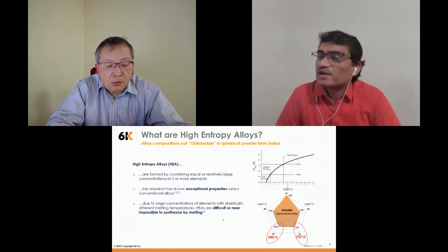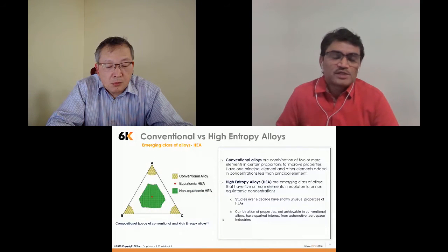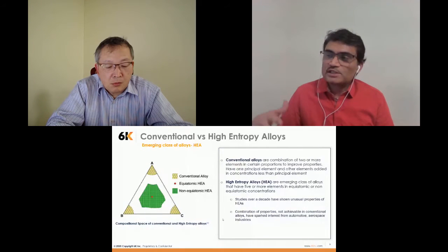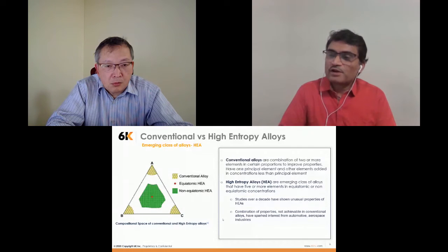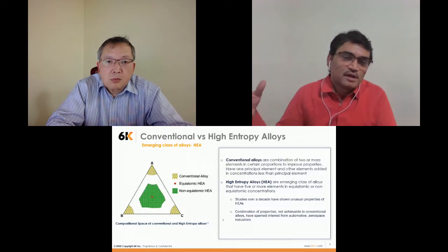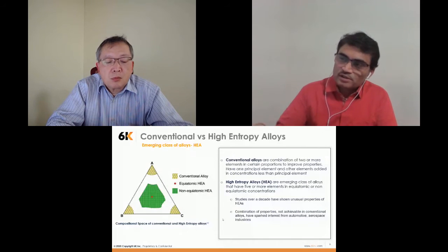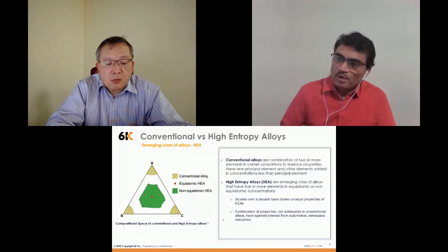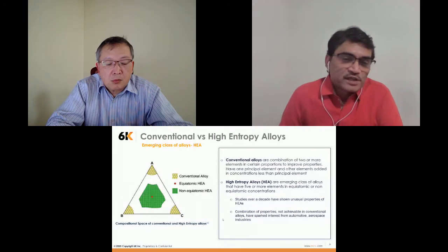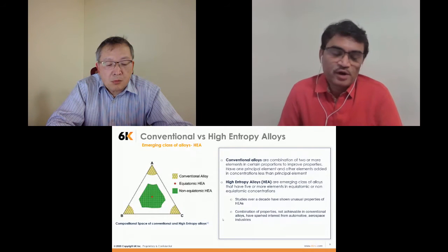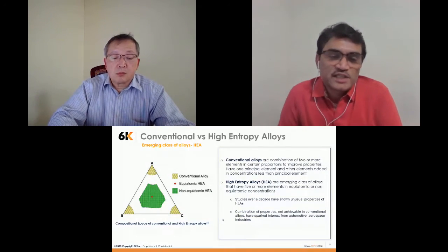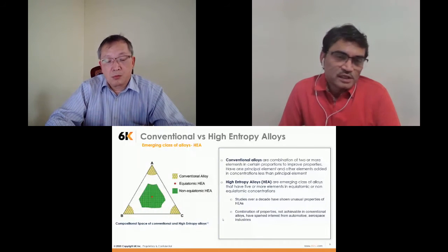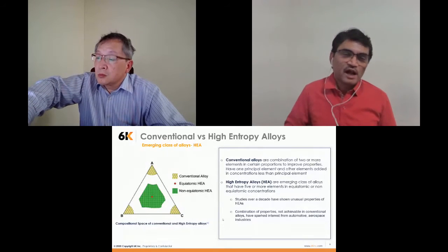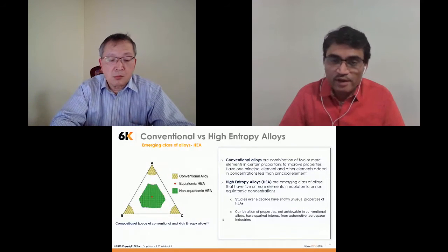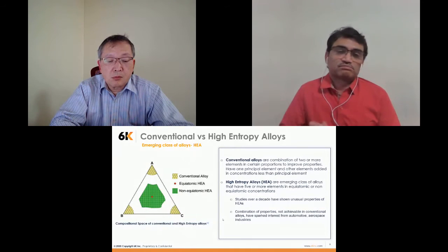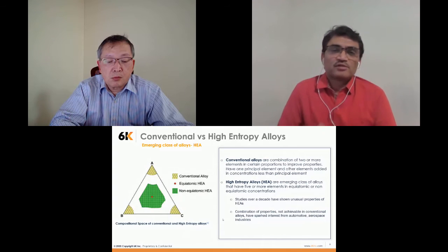So high entropy alloys basically give us a very large design space. If you see this ternary phase diagram, the conventional alloys are concentrated at the apexes of this ternary diagram. So the yellow section in this figure is where the conventional alloys are. The green portion is non-equiatomic high entropy alloys, and the red dot in the center is equiatomic high entropy alloys. So basically, high entropy alloys have a very, very high design space, which is not utilized today, and that we can utilize for different types of alloys, which can give you various combinations of properties.